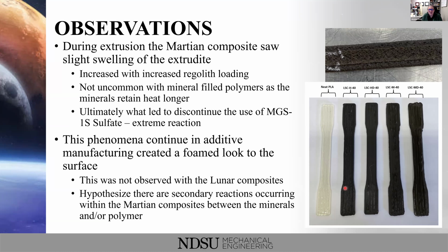And as I said earlier, it's not uncommon, right? We're adding a mineral-filled polymer. It retains heat, the mineral does, and so you're going to see it thermally expand a little bit. But it was an extreme kind of swelling, right? That we did see with the sulfate, but even with the other, like the global simulant and that clay-filled simulant that we printed with, to the point that we almost had a surface that looked like we had foamed our material as opposed to 3D printed with it.